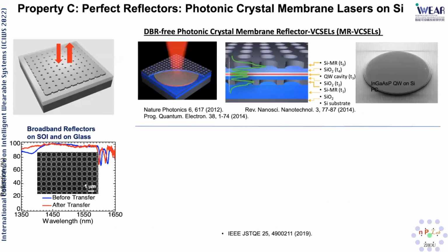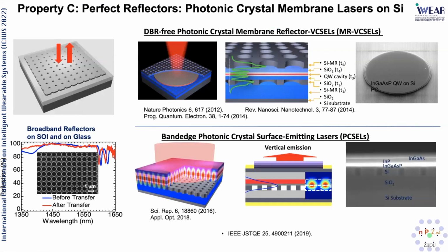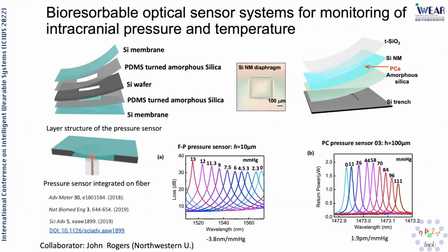And with that, we were able to make different kinds of active devices, lasers. For example, we were able to demonstrate a very thin, a few micron thick surface emitting laser structure, based on this reflector property, and later on using the cavity property of a photonic crystal cavity, with a slightly different design, we can achieve an even thinner structure where you just need one layer of photonic crystal cavity, where you can achieve really high performance lasers, and some of them can be very high power. So that's a few applications on the photonic crystal side for sensing platforms.